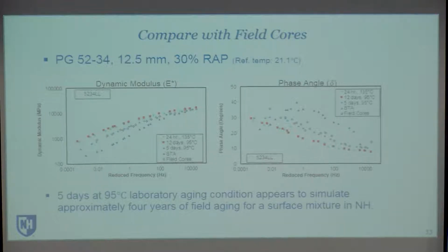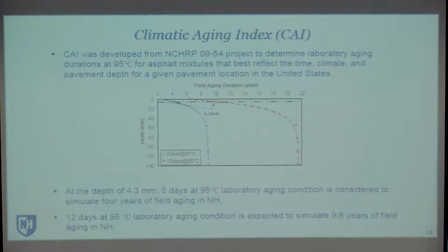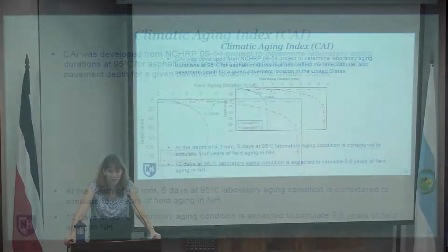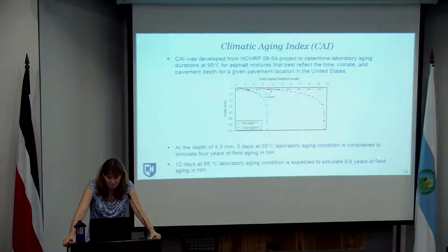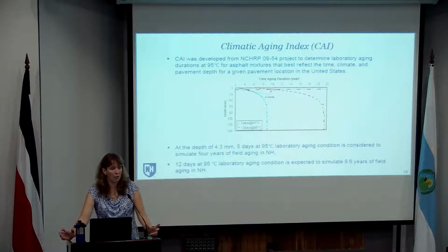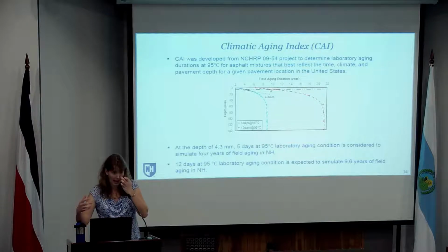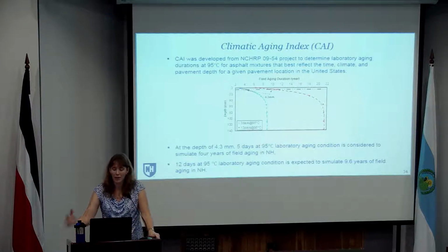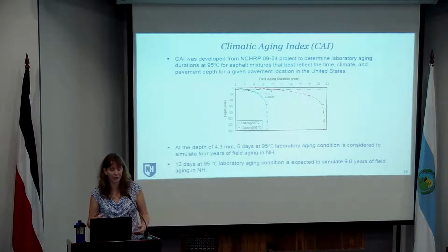So what we did was take this a little bit further with some of the work that was done in the NCHRP 954 project to look at what were the appropriate aging durations at that 95 degrees C that best reflect the time and conditions at particular locations across the United States. So they developed what they called a climate aging index. So we applied that to our conditions to see, with this climate aging index, what depth are we really simulating?